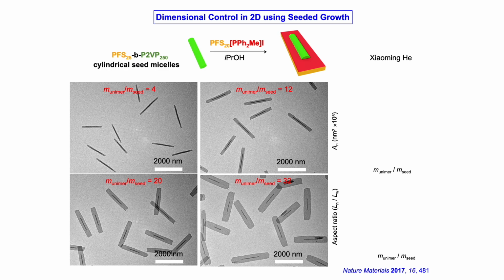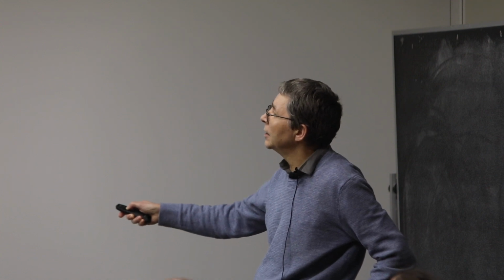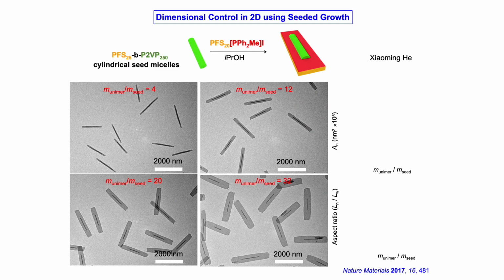So again, you can control the dimensions of these 2D structures by the ratio of the polymer you add to the seed. Here's the ratio, 4, 12, 20, 32. You can see the structures getting bigger. If you plot now the area against the ratio of the polymer you add to the seed, you get a straight line, so you can control the area.